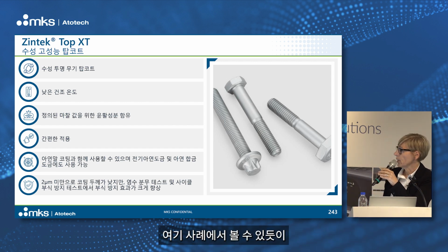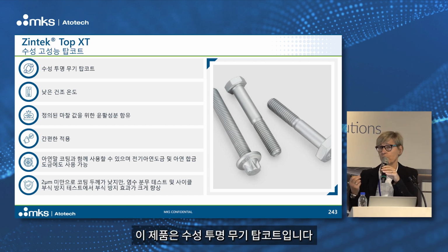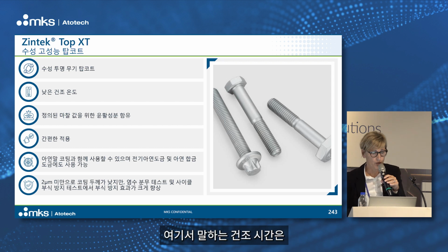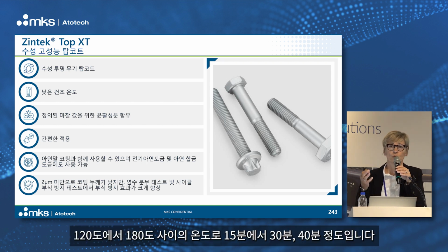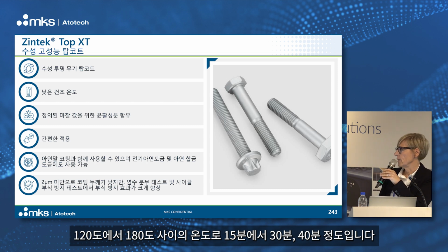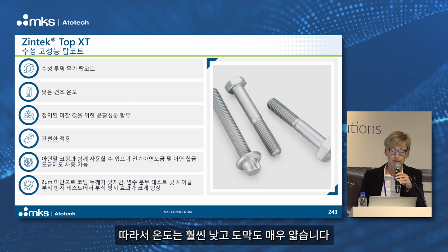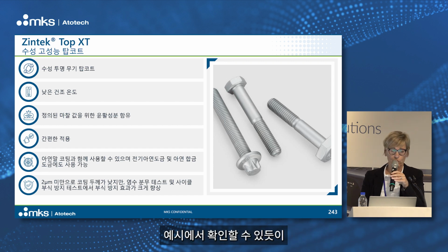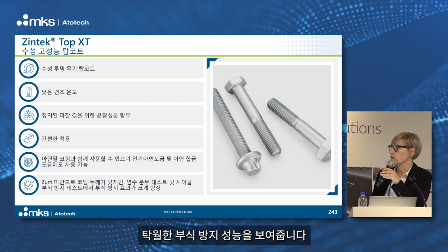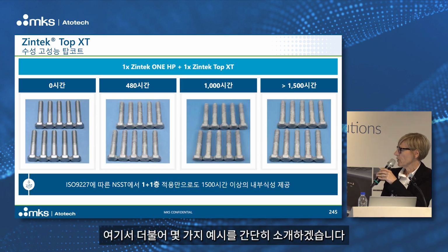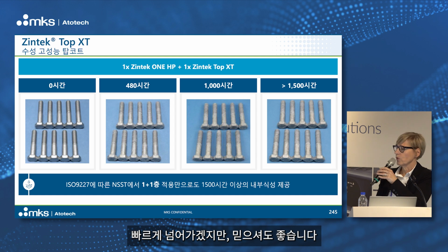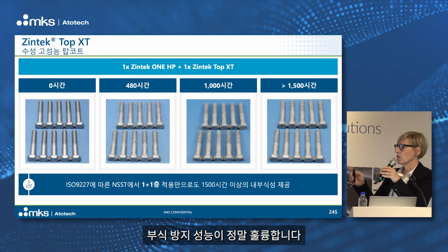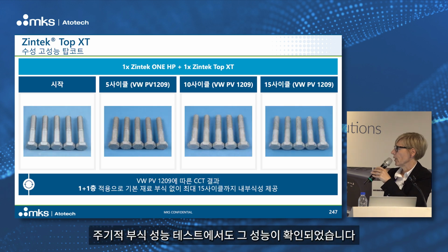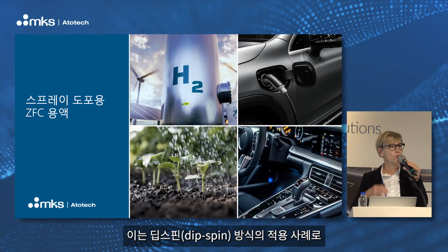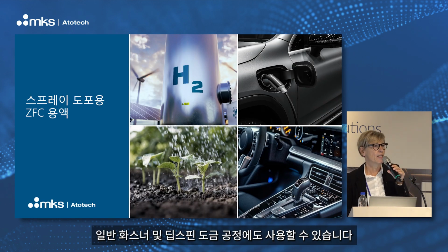You see here in an example that it is a water-based, transparent, inorganic top coat and has a low drying temperature. We are talking here about drying like 15 to 30, 40 minutes at 120 to 180 degrees, so really much lower, and really thin. But despite being very thin, we also will see in the example, it has excellent corrosion performance. We are sharing just some examples, and to save a little bit of time, I go very fast over them, but you can believe the corrosion performance is very good, not only in the neutral salt spray test, but also as we are seeing in the cyclic performance. What we have seen before is for dip spin application, a normal fastener dip spin application, for example.